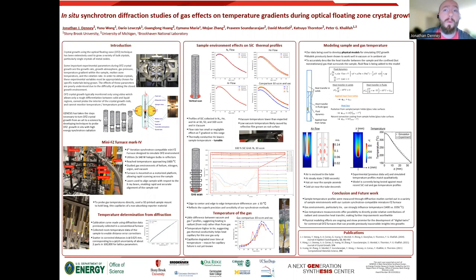OFZ is a method for growing single crystals in which light is focused on a specific region in space and two polycrystal rods are pressed together in that region creating a molten zone. The top or feed rod is passed into the zone and the bottom or seed rod is pulled out of the zone. This allows crystal growth to occur on the seed rod.